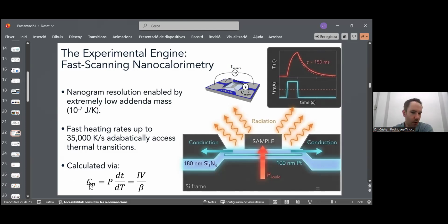We work in differential mode. There is a complex equation here, but basically it is the power we inject divided by the heating rate, where beta is the heating rate. In that way, we can measure the heat capacity during the transformation from glass to liquid in very thin films. This is the important thing here: we can measure the heat capacity and the transformation dynamics of very thin films. 10 nanometers is more than enough to study the